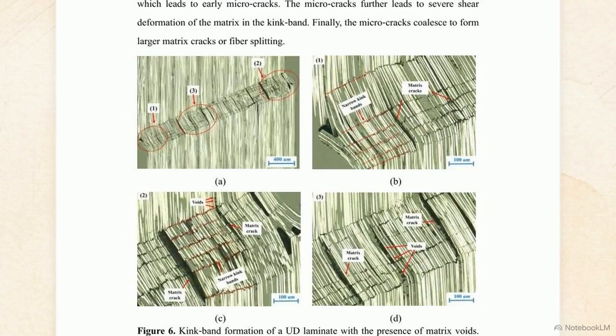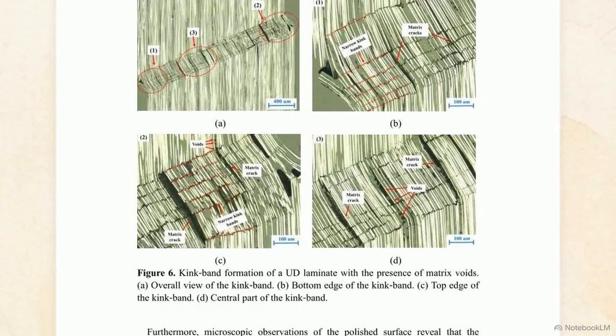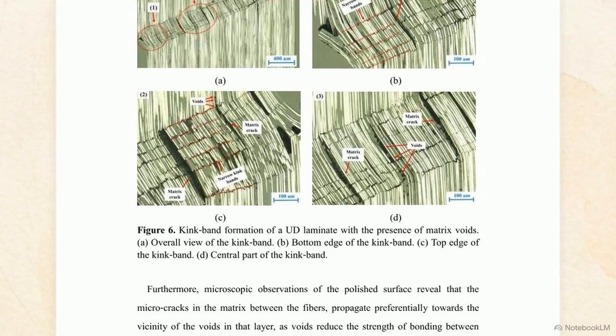In these micrographs, as shear stress exceeds yield strength, matrix microcracks form. The resin tears, losing lateral support. Unanchored fibers tilt cooperatively, rotating from the vertical axis to form a localized microbuckle band. This sharp angular change marks the exact transition to structural failure.